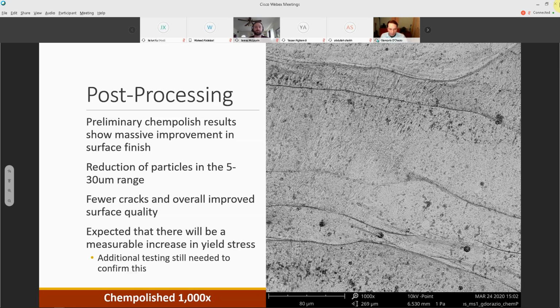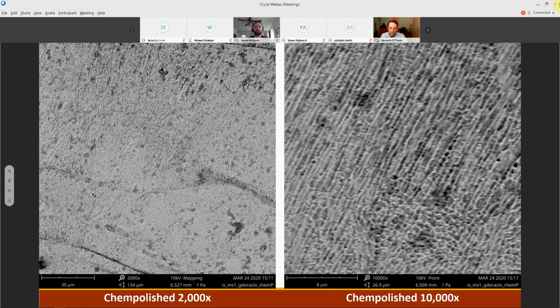This is something that we didn't have an opportunity to test. But you can see to the right there is a chem polished sample at 1,000 times magnification. And taking that, we can look at it 2,000 and 10,000 times on the left and right respectively. And you can see the surface is incredibly uniform and smooth. We don't have any of this particulate that we saw in the pre-polished samples.